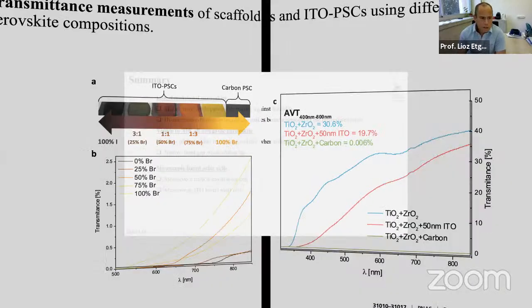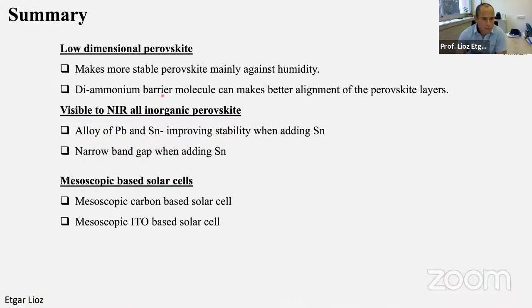By that, I want to finish. So this is the summary. I presented the low-dimensional perovskite, a new concept using diamine, the opportunity to go to the near IR with the perovskite by using lead and tin, and not necessarily that the tin is harming the stability, it is doing the opposite. And finally, 2 new structures in terms of mesoscopic carbon cells and the ITOs that we recently developed.